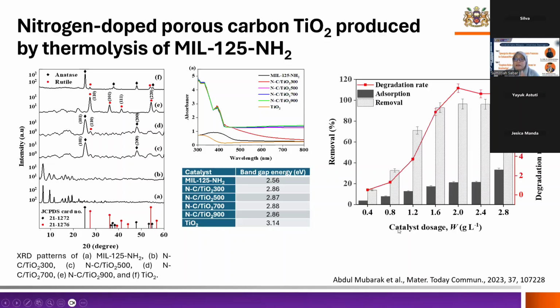And this is the effect of the catalyst dosage for the photocatalytic degradation of methylene blue. We observe that the adsorption increases with the increase of the photocatalyst. But you should also be careful so that the adsorption is not dominant towards the photocatalytic reaction. If not, all the dye will be adsorbed onto the adsorbent and it will not be degraded. We want the pollutant to be degraded and not just adsorbed onto the adsorbent material.